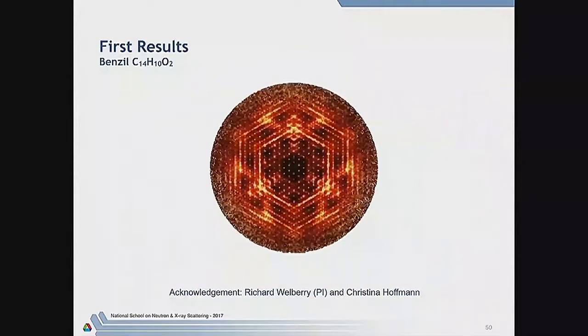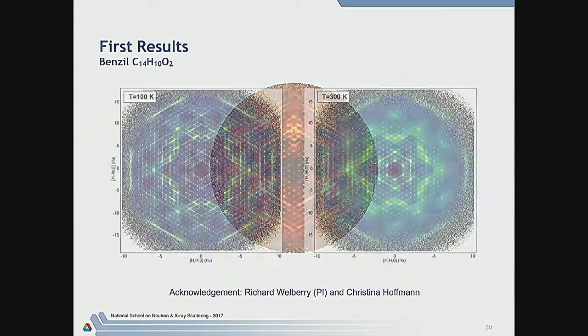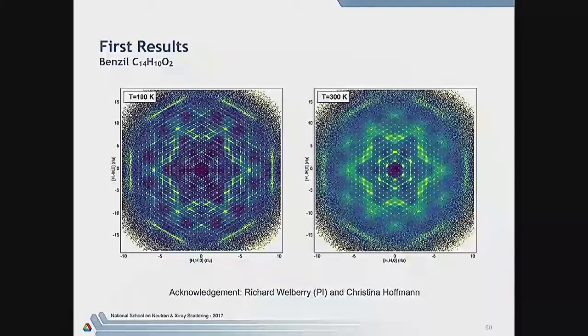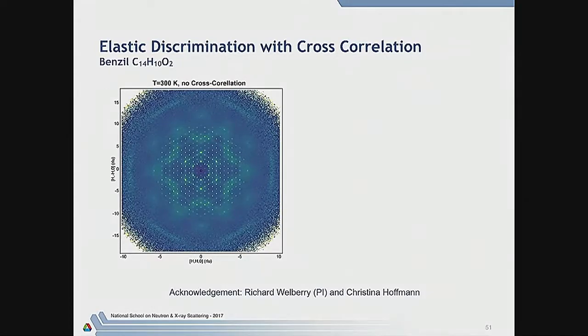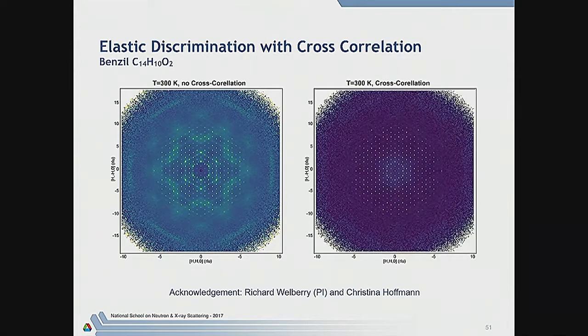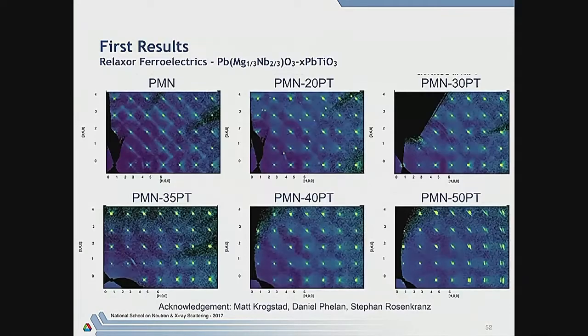We go back to benzil, which they've done, and you get again the same sort of diffuse scattering that you saw on SXD over 14 years ago. But here's the really interesting thing: you see that diffuse scattering here without any cross-correlation. So you're just measuring the total scattering. You put in the cross-correlation, it's gone. So in other words, actually all of the diffuse scattering is dynamic, not just some of it. So cross-correlation works, and it helps to distinguish these things.